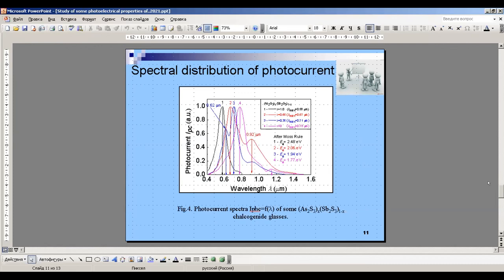Here you can see the photocurrent spectra we obtained for some samples. I don't include all samples because it would be very hard to see. We observed that with increase in the arsenic sulfur compound content, the maximum of photoconductivity shifts towards the infrared region.